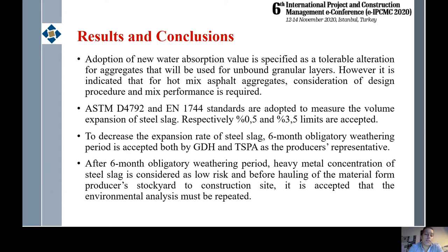ASTM D4792 and EN 1744 standards are adopted to measure the volume expansion of steel slag, with 0.5% and 3.5% accepted respectively. To decrease the expansion rate of steel slag, a 6-month obligatory weathering period is accepted both by the General Directorate of Highways and the Turkish Steel Producers Association as the producers' representative.